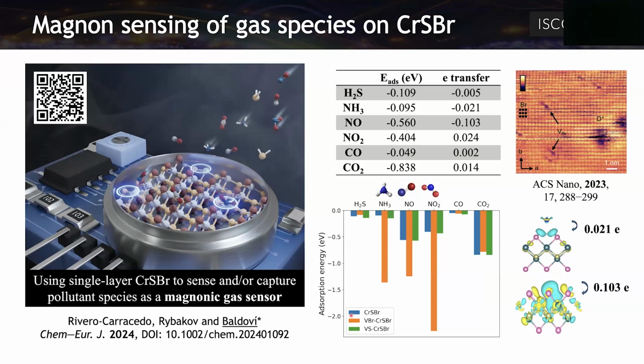So we are comparing here the adsorption energy on pristine chromium sulfur bromide, that is in blue, of these species. And then we add vacancies. We have a supercell. We remove one of the bromides. We relax the structure, and we add the molecules. And we can observe here that for the molecules that have nitrogen, this increases a lot for ammonia, NO, and NO2. And in the case of the vacancies of sulfur, there is some increase also here.